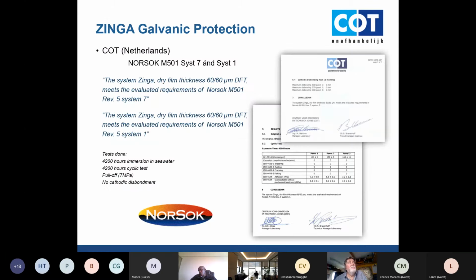We also have certification for NORSOK, which is also one of the industry standards used all over Europe and in other countries. Again, you can see it's 4,200 hours immersion in seawater and 4,200 hours in cyclic testing. And the pull-off value is 7 megapascal. So it's not an easy test to pass. A lot of paints fail these tests. In fact, they fail them halfway through.